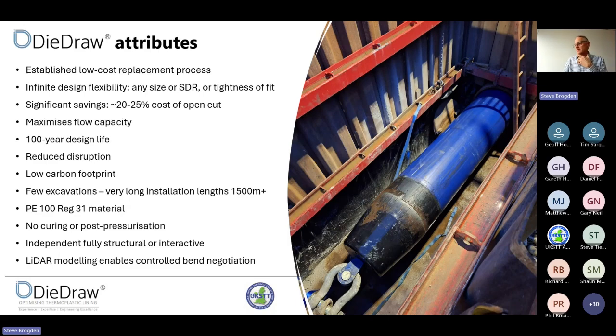Obviously, it's Reg 31 compliant, and it's a natural process. We don't need to cure or post-pressurize. We can have an independent, fully structural liner, and we've got modelling techniques that enable us to go through bends. We've developed that further, because the limit with LiDAR had been that you cannot get the equipment in a pipe that's less than about 500 millimeters. I think we've found a way around that now, and we're using a laser system that can get us the data so that we can map the interior of the pipe at the same time as the camera inspection process, so that we can input that data into our software and then adjust our die design, which is a very flexible design.